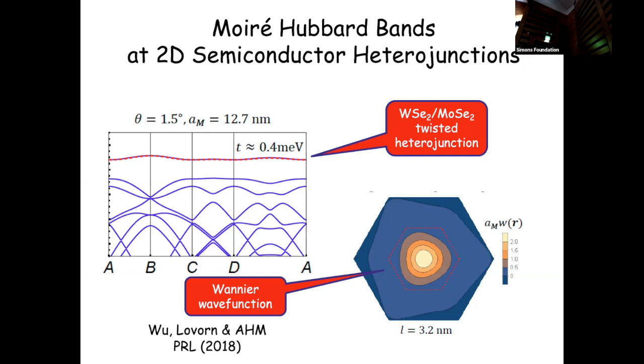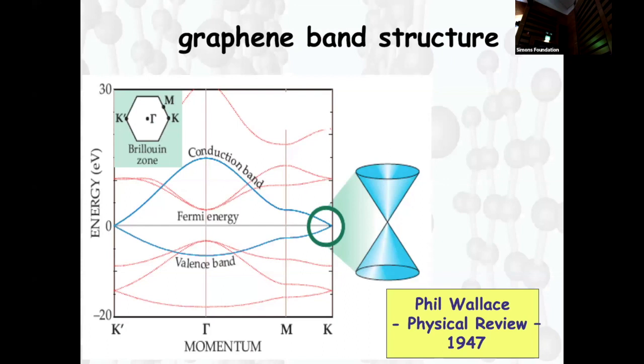Of course, there are some important differences because the attractive potential is not a nuclear or ionic attractive potential. It's a periodic attractive potential, just a local minimum. So that does make some differences, but things are quite similar to, let's say, a cold atom system. And by varying the twist angle, and by varying the interaction strength, for example by changing the distance to the gates, you can get into regimes. I think not all of this has been demonstrated yet. I think people are seeing basically Hubbard physics, but I expect people will be able to see heavy fermion physics, frustrated magnetism, and many other things that are of interest in the system.